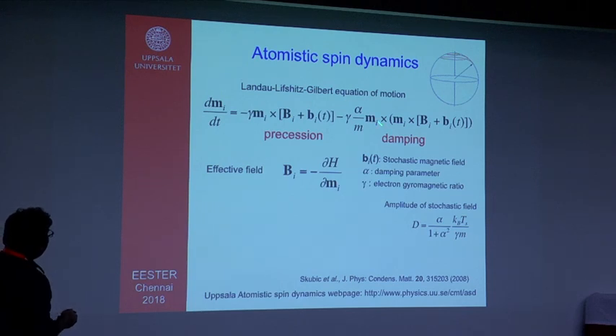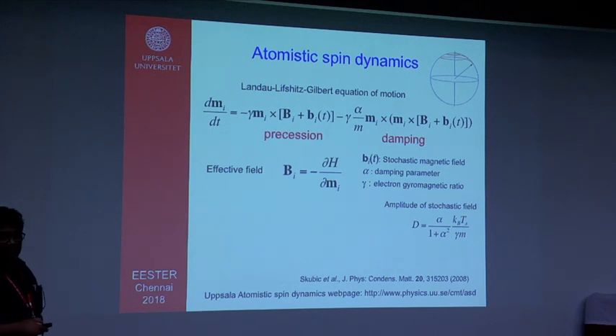Now, there are several terms here. This is a stochastic magnetic field that you can put in with Gaussian white noise. The amplitude of the stochastic field is related to the spin temperature. So when you pass the spin temperature into it, that comes directly here and gives you the amplitude of the stochastic field, and it basically involves random numbers. And B_i, capital B_i, is the effective field, which is the derivative of the spin Hamiltonian with respect to the local magnetic moment.